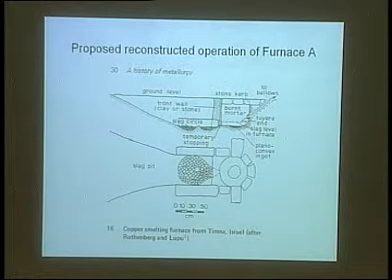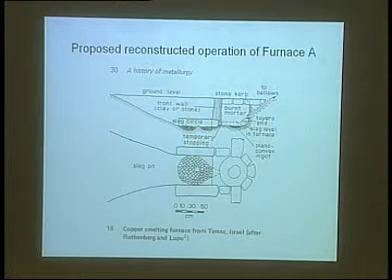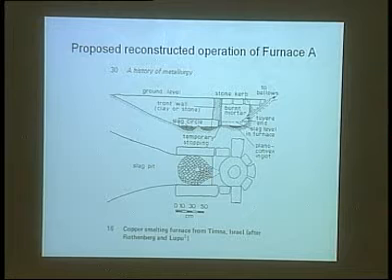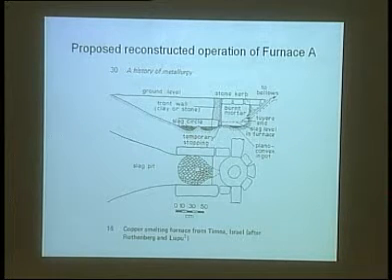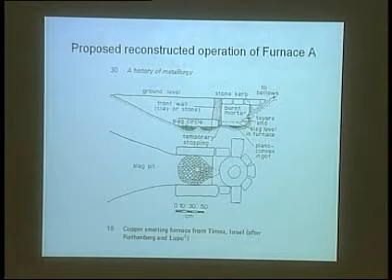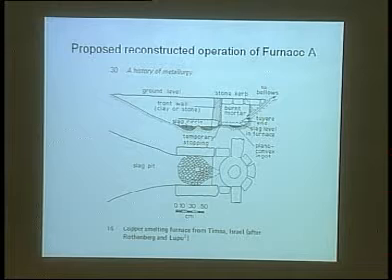The whole mass here would eventually reach a temperature that the slag, remember all the ingredients are going in, reaches its melting point. That builds up in the bottom of the furnace. Reduction's taking place. A plano-convex ingot was suggested as the product from the bottom. And we've got some examples of plano-convex ingots here that we've made in some of the experiments as well. And to make it a little easier to get to the copper, the molten slag would be drained out of the furnace like this. Okay?